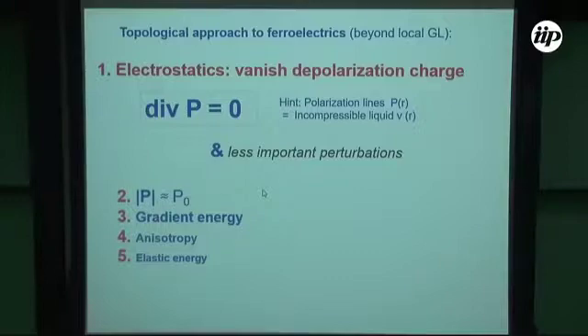But of course, if you are quite far from the transition, so we are in the minimum of the Ginzburg-Landau functional, polarization would like to be as close as possible to the uniform value. Of course, after that comes the minimization of gradient energy, the anisotropy effect, but for this case we are also trying to look for the less anisotropic system to not mix everything together, and finally also elasticity. But the idea to describe it qualitatively is first to state that the polarization fields are solenoidal.